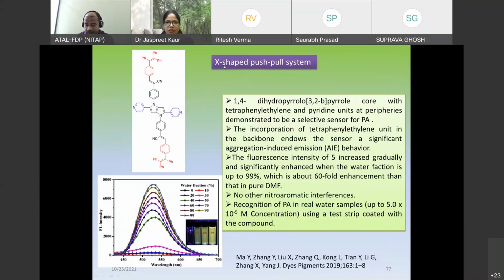So next one is the X-shaped push-pull system. Now these are other compounds. Yes, we can have a dihydropyrrole. So here we have tetraphenylethylene and pyridine units at the para positions. These compounds also show aggregation-induced phenomena. When the water fraction was 99%, it shows a 60-fold enhancement compared to pure DMF. So there was no interference from other nitroaromatics, and real water sampling is also there. It also detects picric acid in a real water sample using test strips coated with this X-shaped organic molecule.